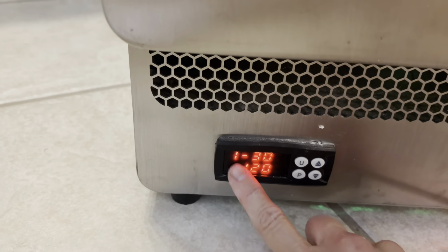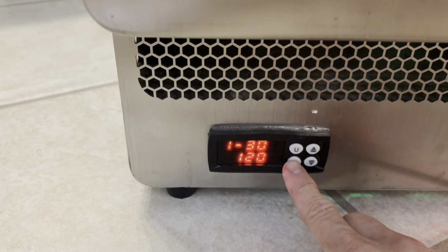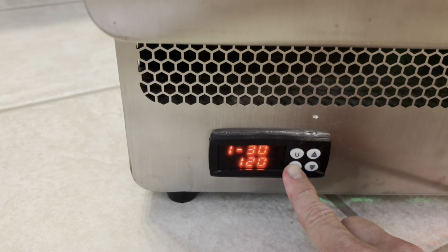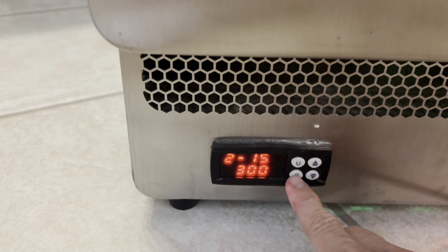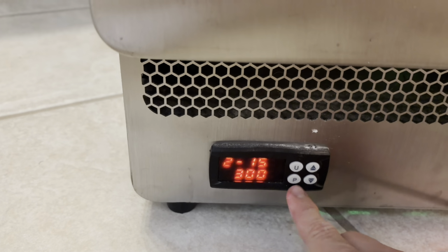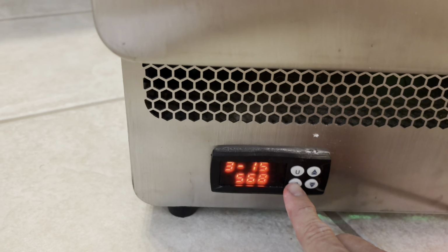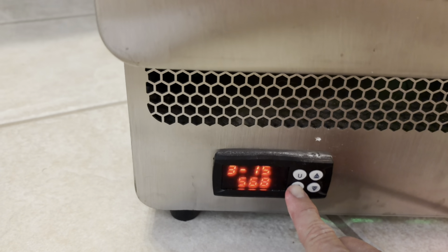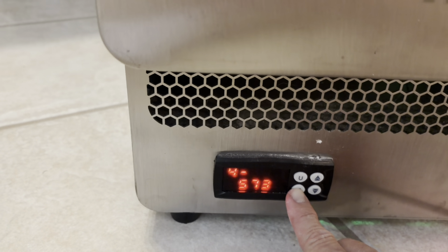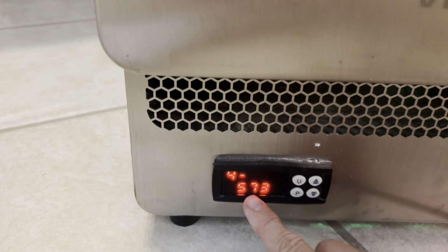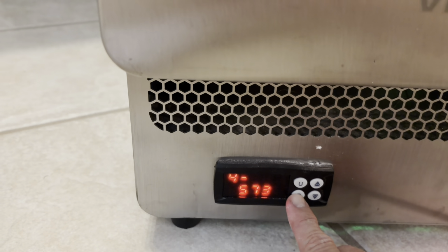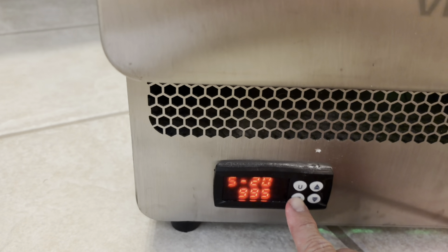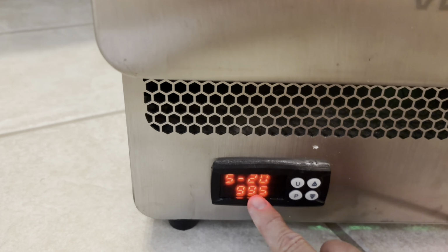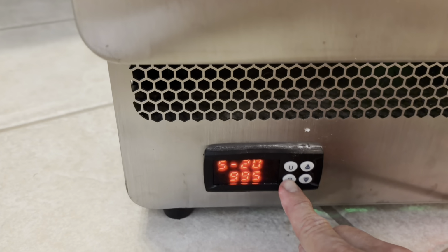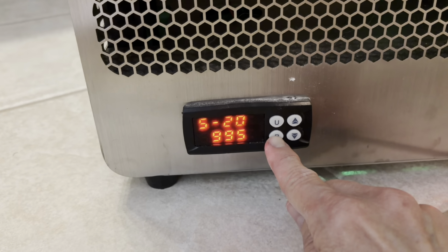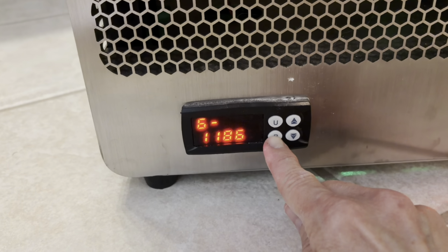It works. So if you run back through it, here are the settings. Stage 1, 30 minutes, 120 degrees. Stage 2, 15 minutes, 300 degrees. Stage 3, 15 minutes, 568 degrees centigrade. Stage 4, 25 minutes, 573 degrees centigrade. Stage 5, 20 minutes, 995 degrees. I have these strange numbers in here because my kiln's a little hot and I am factoring that in. Okay. Stage 6, 1186 degrees for 10 minutes.